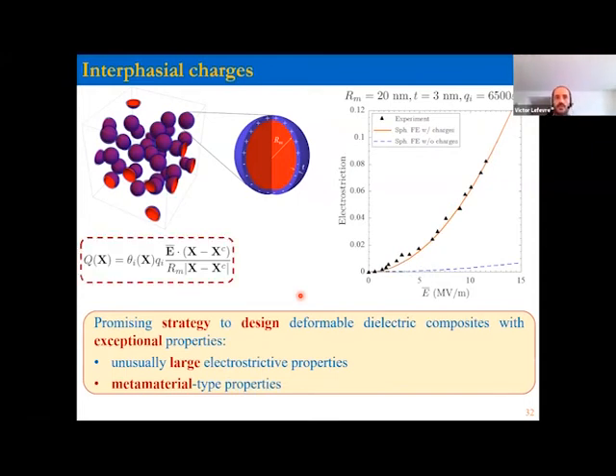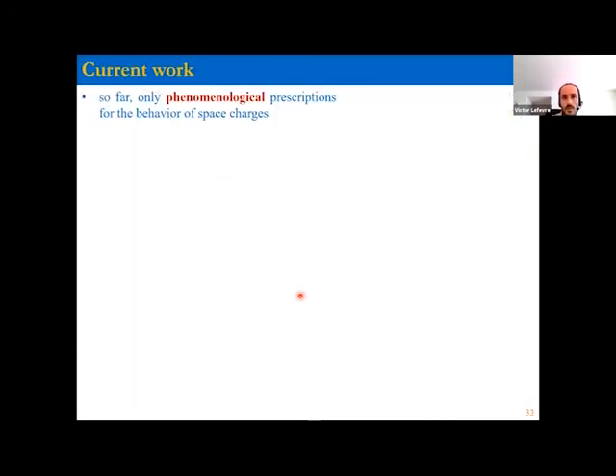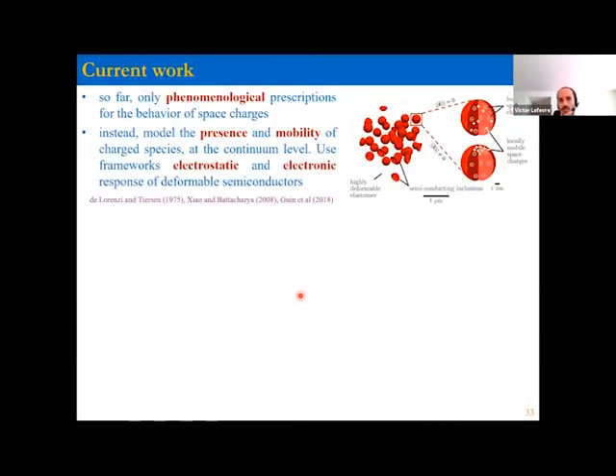There's a catch about this. This we had to prescribe. This is purely phenomenological because nobody knows if there are space charges in the first place and how they localize and distribute themselves around the particles. That's something that we had to prescribe phenomenologically. So what we are looking to do now is to use instead a physics-based model for the presence and mobility of these charges at the continuum level. So using ideas that have been used before for deformable semiconductors, where now you are using physics to describe how the charges move around the material and how they distribute themselves.